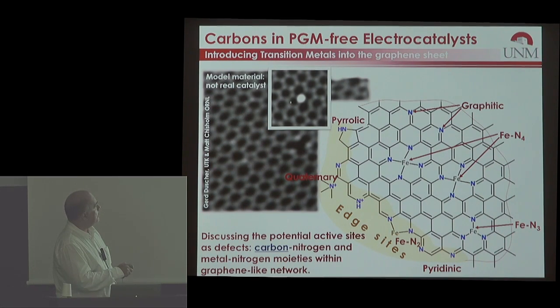And here is evidence of an iron residing in a double vacancy. This, however, is not a catalyst. This is a model graphene sheet obtained on copper that has been bombarded with nitrogen and then bombarded with iron atomically, just to obtain information on whether such structures are possible.